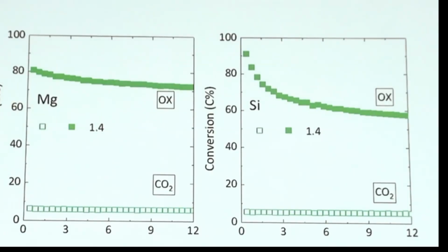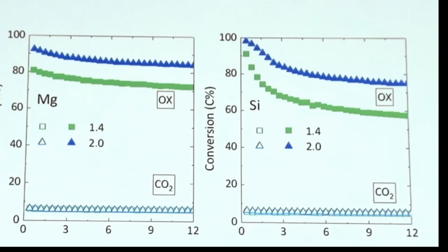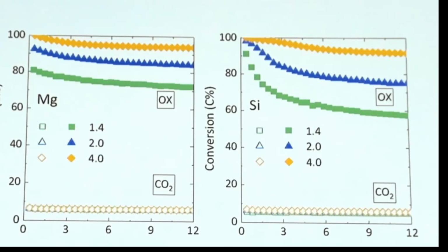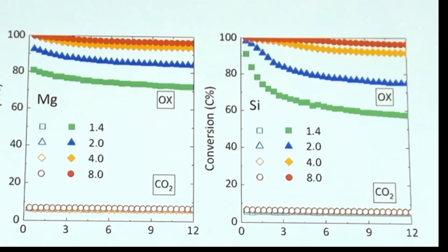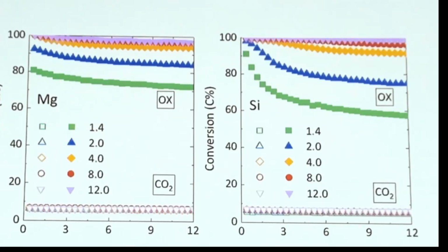Now, when we increase the amount of MAPO in the structures or in the catalyst bed, then we see that we have better performance for both materials. And then at some point, we see that they become very similar. And then we see in the end, actually, that the silicon material seems to be at least as good as the magnesium material.